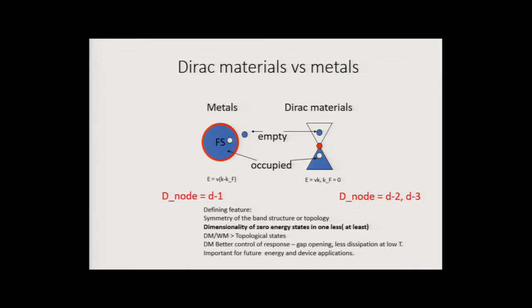So it is obvious that going from d minus 1, this 2-dimensional surface in 3D, to something which has one whole integer dimension less is not an accident. You just cannot do it by accident. There is clearly something else going on. What's happening is that this massive reduction of the zero energy or low energy excitations is coming because you have either symmetry or topology that forces this particular property of the band structure. Just an example: what you can see in the Dirac material is a very stable and robust crossing point that is not changed unless you work hard on this or unless you break the symmetry.